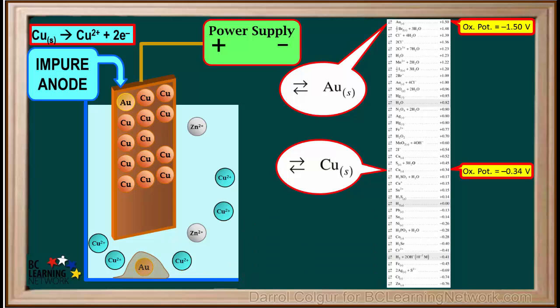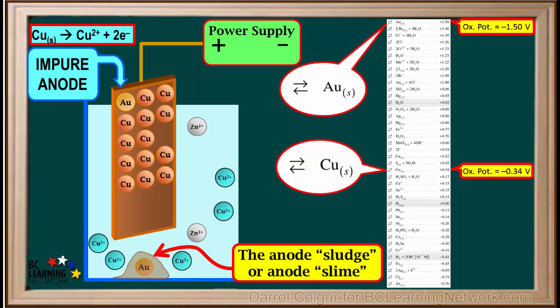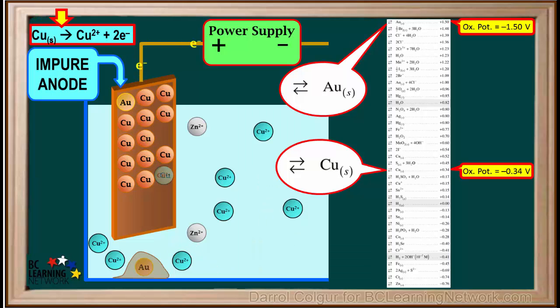A combination of metals that are above copper on the right side of the table, which do not get oxidized such as silver and gold, along with the non-metallic impurities that were in the copper, will collect underneath the anode. This is often called the anode sludge. Later on, this is refined to extract the precious metals from it. Copper atoms continue to be oxidized to Cu2+ ions that go into the solution.